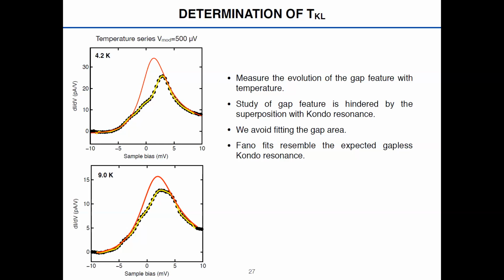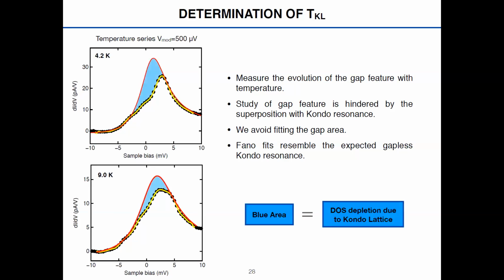We're going to fit our spectra with the Fano line shape, but we're going to avoid fitting the area where the gap appears, so this area from -3 millivolts to 3 millivolts. So we're going to fit this area here of the spectra and this area here. And we believe that this Fano line shape should represent the Kondo resonance without the gap, so the pristine Kondo. If we then fit the experimental values with a polynomial function, we can calculate this blue area that we believe is related to how the density of states is depleted due to the appearance of this Kondo Lattice gap.